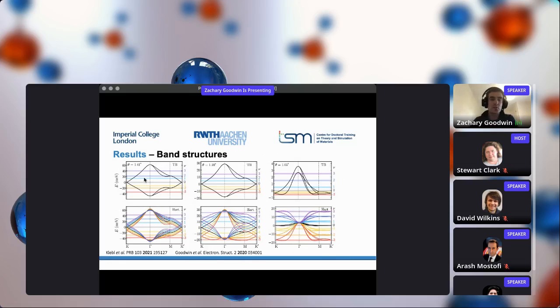But for a twist angle of 1.4 degrees, which is somewhat away from the magic angle, these effects of the electronic interactions are fairly weak. But as we go to a twist angle closer, say 1.2 degrees, these interactions become a more dominant energy scale, and what we find is that they induce interaction-driven band flattening, in addition to the band flattening from the twist angle. And right at the magic angle, these electron interactions are actually the dominant energy scale. As you can see, the electronic band structure changes really quite significantly.